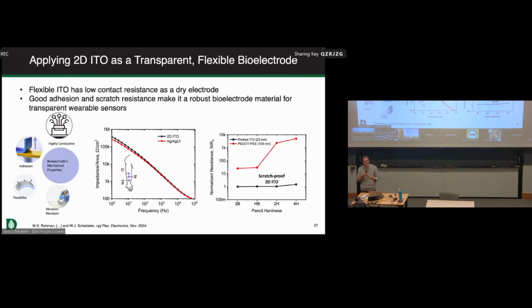So my student Cypher was developing some different applications for this two-dimensional indium tin oxide, and one of the applications that stood out to us was the ability to make bioelectrodes that were also transparent. It's an idea that some of my colleagues have already exploited in other kinds of biomedical devices. But indium tin oxide, it turns out, has pretty impressive properties as an interface to the skin. It can have a relatively low contact impedance. If we're trying to make an interface, for example, to take electrocardiography measurements, then that contact impedance is a good sign for us that we can get high SNR.